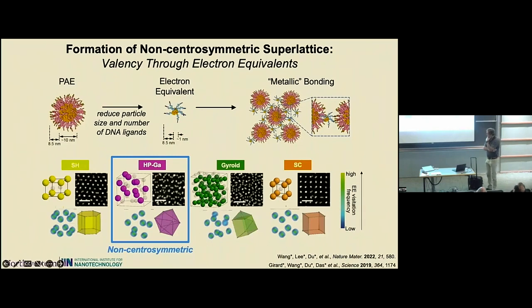And so what we found is that in certain cases, you can take large particles with these tiny electron equivalents, and they will migrate through the lattice and then adopt areas of local concentration that effectively create a geometry that allows for a specific type of bonding, right? So you can kind of think about it as electrons occupying certain sites, and they're repelling one another to adopt a specific geometry that leads then to a connectivity that is more defined than the random movement throughout the entire lattice. And again, that's very similar, at least conceptually, in the way we think about things like VSEPR, and that's allowed us to now realize a variety of other architectures, including the ones shown on this particular slide.